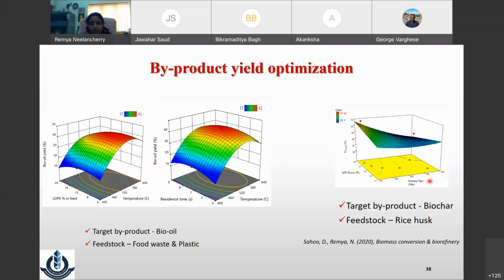Now we have also done the pyrolysis of rice husk. So in this study, we have optimized the bio oil production, and of course, around 50% of bio oil could be generated with comparatively high quality. And in the rice husk, again, the biochar could be produced with an excellent quality compared to the carbonization or the conventional pyrolysis or torrefaction process.